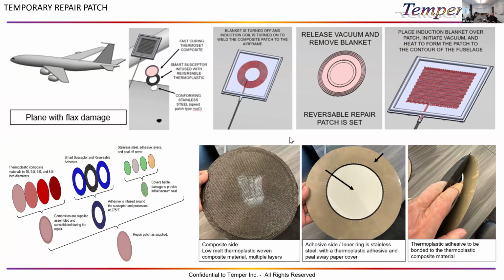We also took that to a new level, and recently came up with a repair patch. So this repair patch concept uses either a thermoplastic or thermoset, but in the simplest form, it would be a thermoset. And let's say that the thermoset was triggered to a 250-degree temperature range for the resin. The smart susceptor on the backside would be with say 275 degrees.